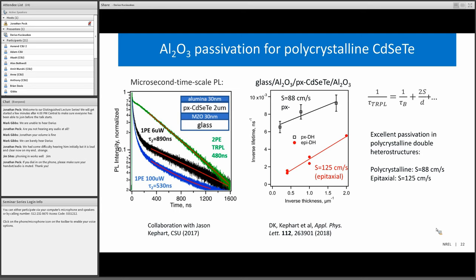When the sample thickness is varied and the inverse of the lifetime is plotted, the slope of this graph is the recombination velocity, as shown by the formula on the top right. And in this case, recombination velocity is less than 100 in the polycrystalline material, which is about the same as it is in the epitaxial material. So basically, the passivation can be very, very good. Of course, these are insulating samples, so it's a challenge to transfer all of these results into the actual device fabrication, and that is an active research area.